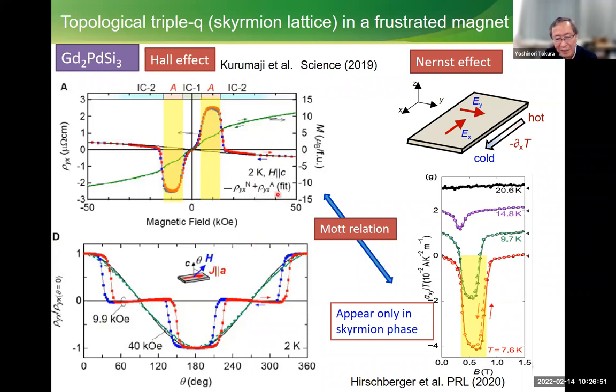And the important point we don't describe here is that the anomalous Hall effect, topological Hall effect, and this topological Nernst effect are related with each other by the so-called Mott relation. The Mott relation is confirmed to hold in this system by changing the chemical potential in this compound. That means we are always talking about the real space topologies, but imagine a Berry curvature itself is also generated in the momentum space, and this momentum space relation is also indispensable for this observation.